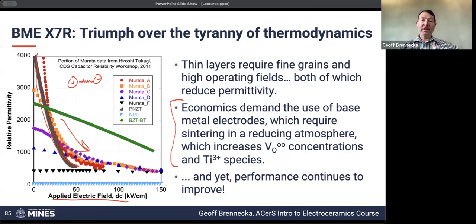So we have to keep the nickel metallic, and we have to keep the barium titanate oxidized, which is another reason that we throw in a lot of these acceptor dopants, the lanthanides and manganese as well. Because if we end up forming titanium 3+ species, so you end up with titanium 4+ next to a titanium 3+, you can actually get electrons hopping between the two. And that leads to what's called polaron conduction. So it's essentially electrons hopping from one species to the next, and this can happen when they are nearby one another, and it's a species that can change valence, and that just leads to another leakage pathway.